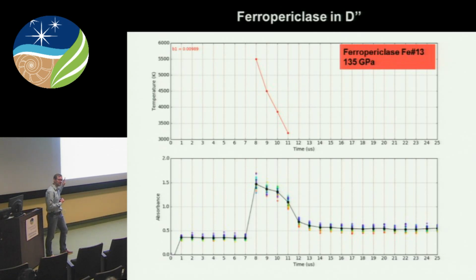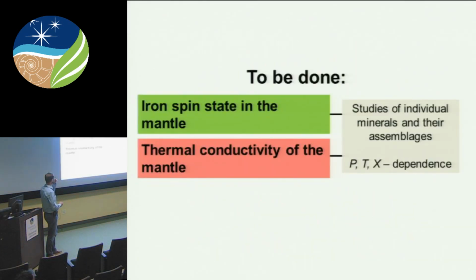ferropericlase is extremely opaque at D double prime conditions, and because it also has a spectrum to it, you can see how it absorbs much less on the red wavelengths than it does on the blue, and that trend is also preserved at high temperature, which means that you basically get an absorption edge shifted into the near infrared range, and that must affect electrical properties of the mineral. So basically, ferropericlase exhibits a semiconducting-like behavior in this temperature range and at this pressure. One instant conclusion that you can think of is that ferropericlase, because it probably has a much higher electrical conductivity at high temperature than it does at room temperature, may govern the electromagnetic coupling of the core and mantle and may be responsible for the transfer of Lorentz torques into the mantle.